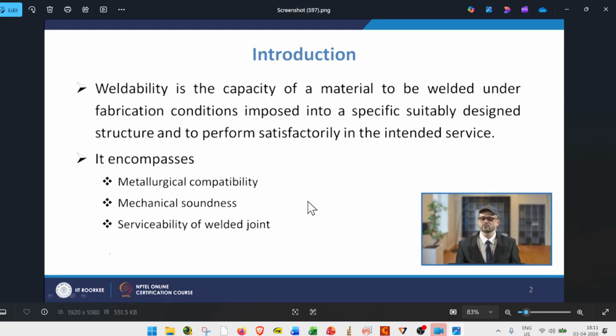First is the metallurgical compatibility. If, while doing the welding, any precipitations are forming, or any microstructure changes are occurring in the weld bead, or any segregation of the elements is taking place, we have to consider those things. And mechanical soundness: in the welded joint, if you do any tensile testing, the base metal should fail before the weld joint. That is the general consideration for a good weld.